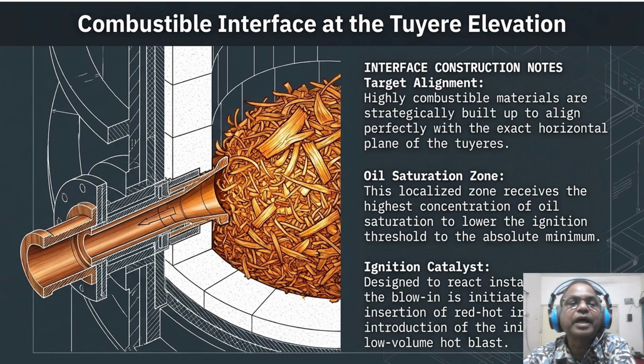So the target alignment node is critical. These materials are built up to align perfectly with the horizontal plane of the tuyeres. This ensures that whether you initiate the blow-in with red hot iron bars or a low volume hot blast, the reaction is instantaneous. Delayed ignition at the tuyere leads to gas buildup in the dust catcher and the gas cleaning system, which can result in a dangerous explosion. We pack these tuyeres with oil soaked wood to guarantee that the second the oxygen hits, we have the fire.